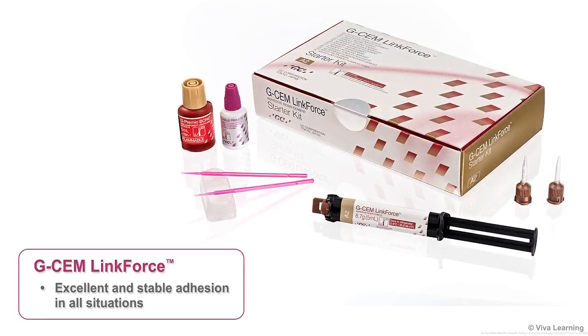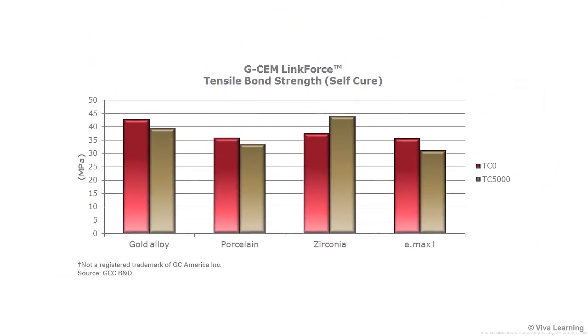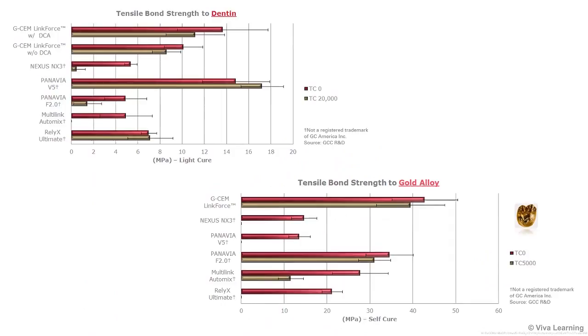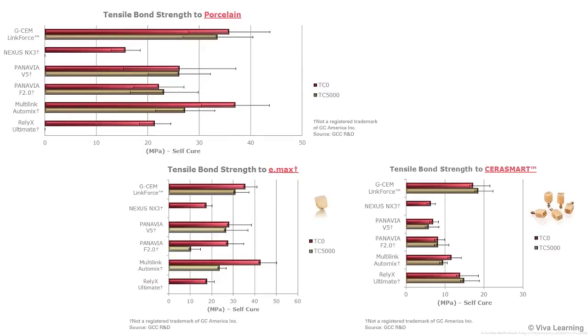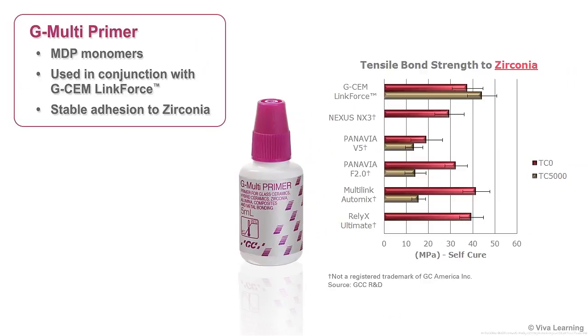G-CEM LinkForce provides excellent and stable adhesion in all situations. This chart illustrates its tensile bond strength to 4 different substrates before and after thermocycling. G-CEM LinkForce's bond strength outperforms most competitive products in most situations, including when used to bond to dentin, gold alloy, porcelain, Emax, and hybrid ceramics, such as GC America's CeraSmart. Thanks to the MDP monomers in G-Multi-Primer, a product that is used in conjunction with G-CEM LinkForce, stable adhesion to zirconia can be achieved as well.